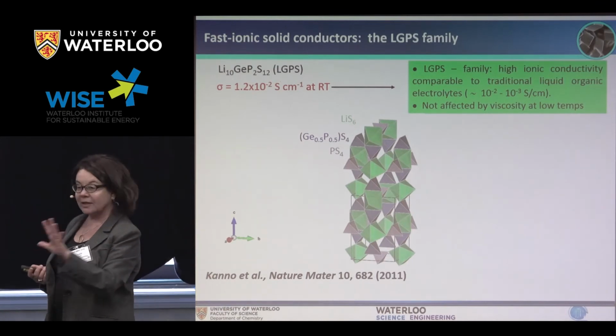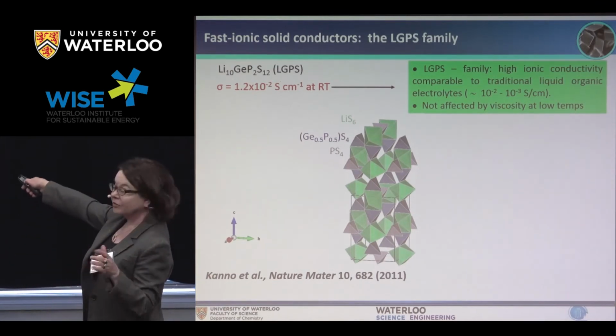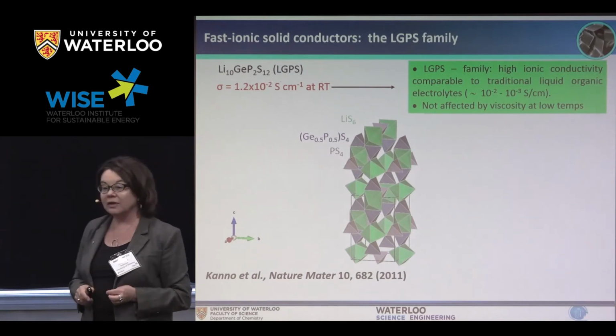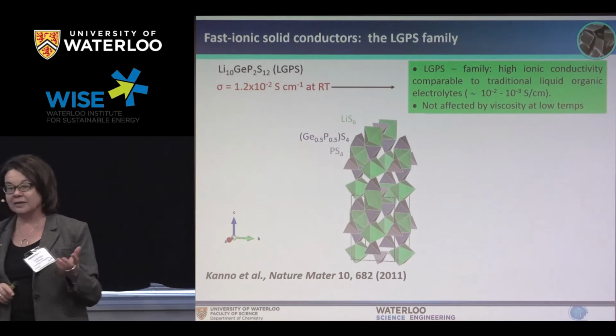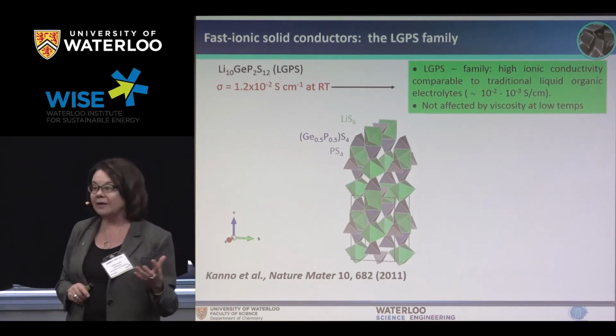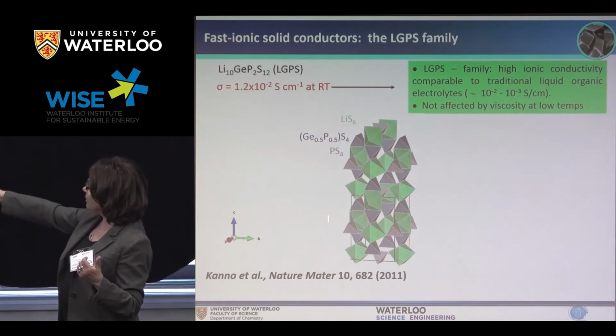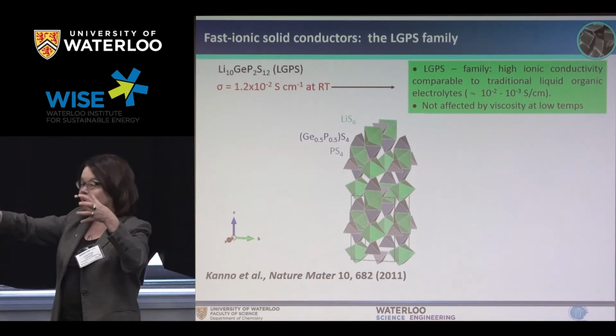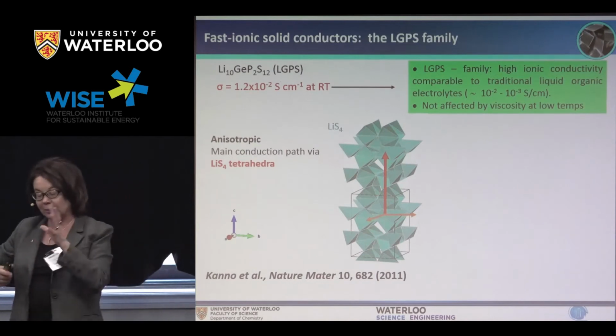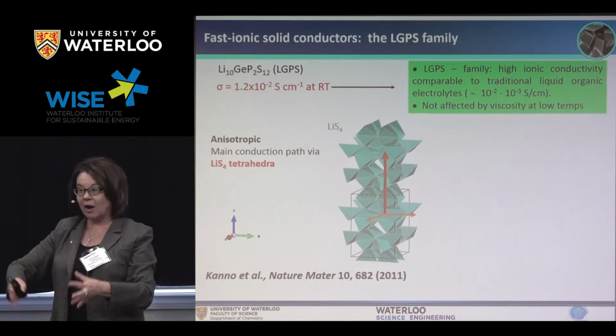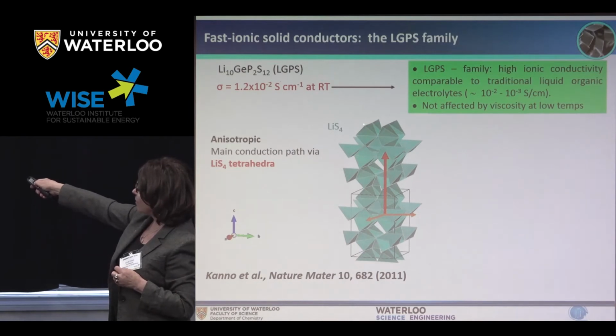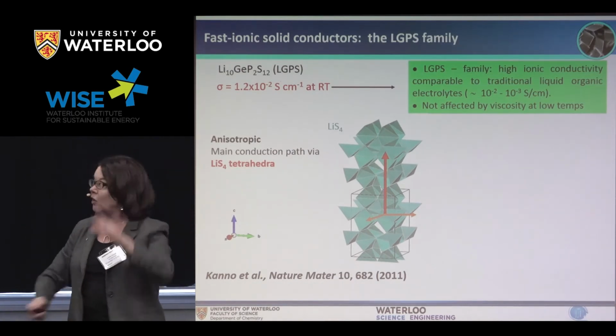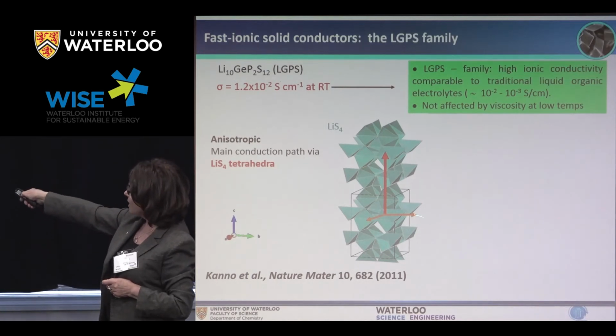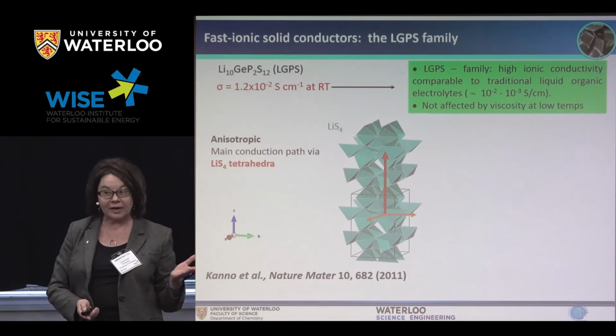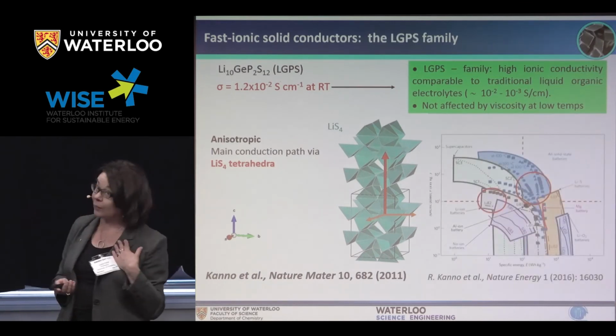So I know you're not chemists, but it's a fairly simple concept. So the first is that these materials actually have a conductivity that is very, very similar to a liquid electrolyte. And that, as I said, if you're a chemist, you find that remarkable, because these ions have to run around in solids. And they do so by having this complicated framework built of these little, we call them tetrahedral building blocks, and they form this rigid sort of parking lot-like structure. And superimposed upon that is this framework of these lithium ions, they're actually bound by sulfur atoms, and the lithium ions literally flow along these channels, along this axis and along this plane. And they flow with a conductivity similar to that of a liquid electrolyte.